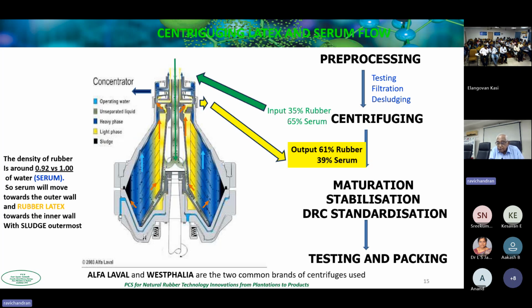So that's the centrifuging stage, but we still have to mature the latex. We have to stabilize the latex. We have to standardize the latex. And that takes about a month. You have to keep it. What happens during that period? There's hydrolysis of the phospholipids. You get the formation of natural fatty acids that act as natural stabilizers for latex.